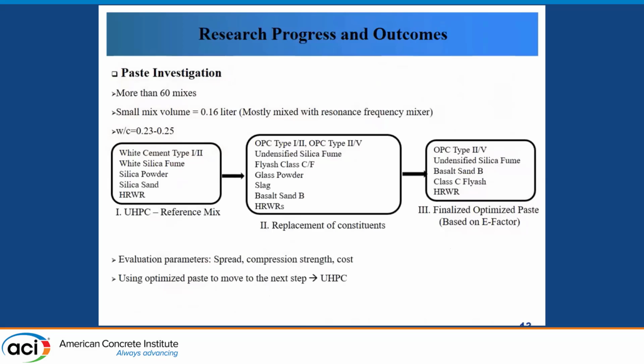Basically, this research has been broadly divided into two parts. First, we started with the paste investigation, followed by the UHPC concrete investigation. We did more than 60 paste mixes, usually small in volume, like 0.16 liter, mostly mixed with the resonance frequency mixer with water cement ratio of 0.23 to 0.25.